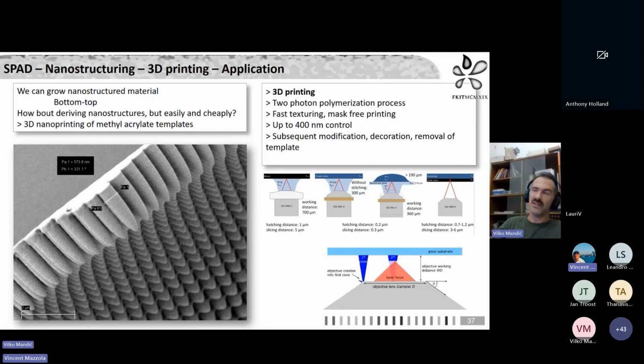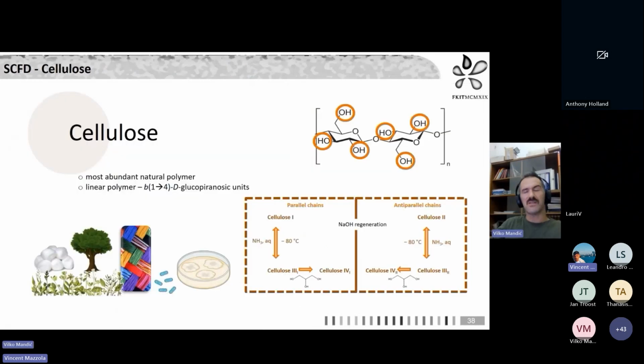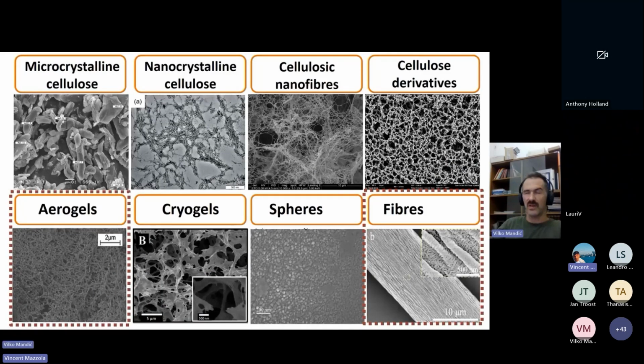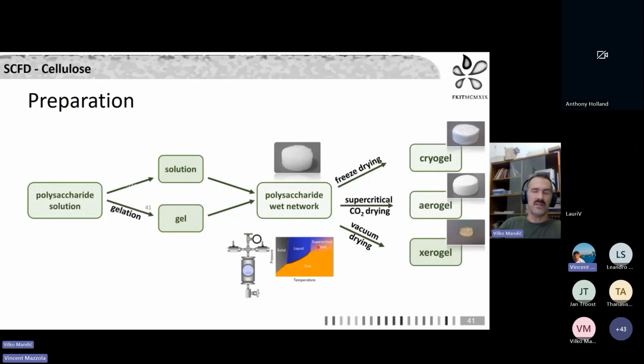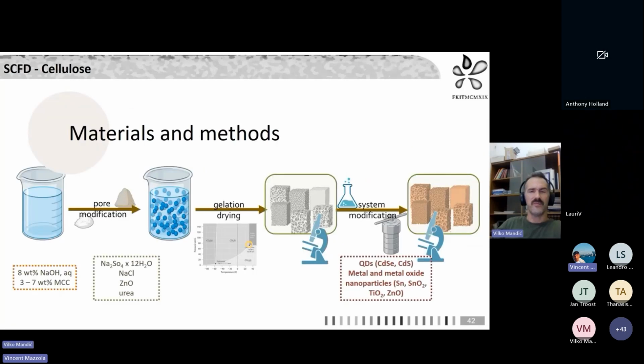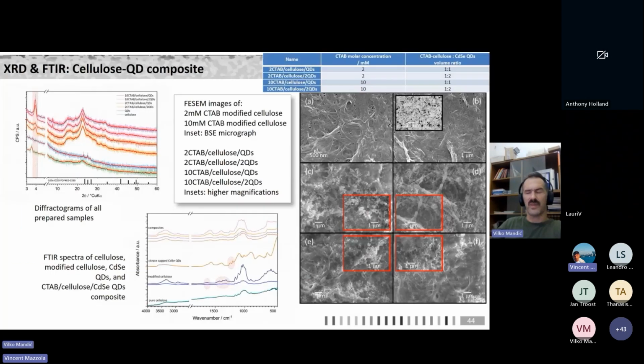I'm just going to talk about cellulose because this is, in contrast to the previous method, super easy to make. You can make a large-scale cellulose without spending days and nights on the printing machine. And obviously, you can see that the morphology of the cellulose can open up everything. So it can be a carrier. One other thing that a cellulose carrier can have, and I'm just going to skip the synthesis, is the ability to react with water. So basically cellulose is swelling, and that swelling, or water, is conductive, which means that this kind of material is inherently suitable, because of the electric conduction, to serve as a sensor.